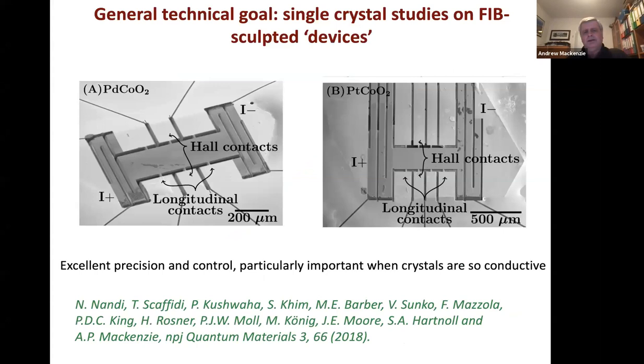So the other kind of thing that we've been able to make use of, which again was absolutely not available to the DuPont guys 50 years ago, is that we want to do very high precision and very well controlled transport measurements. That's particularly important when the crystals are so conductive at low temperatures. Otherwise you would have to put huge currents in to get easily measurable voltages from them. So what we do is we sculpt them down into well-defined devices. These are pseudo bulk devices.